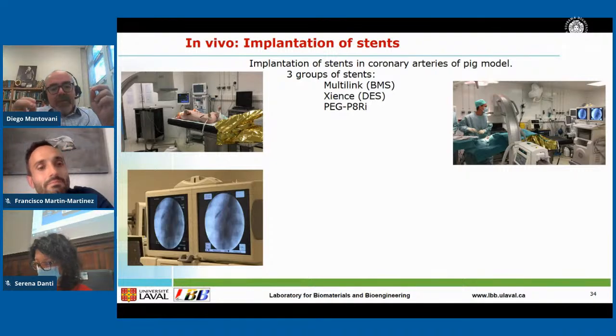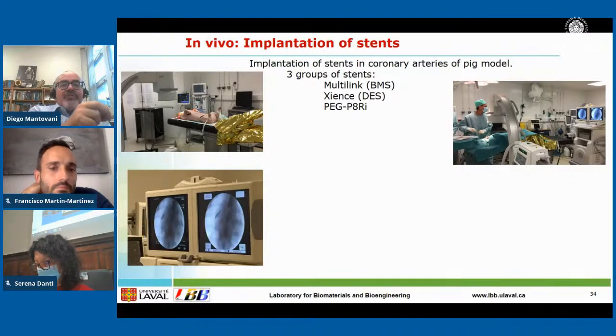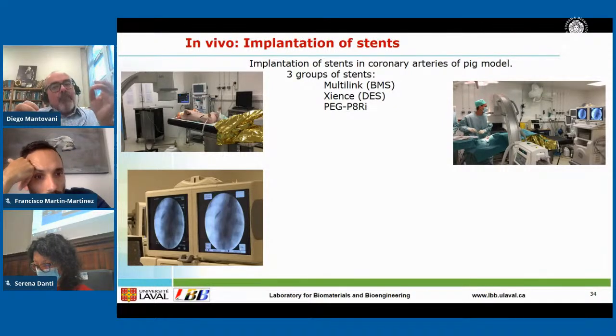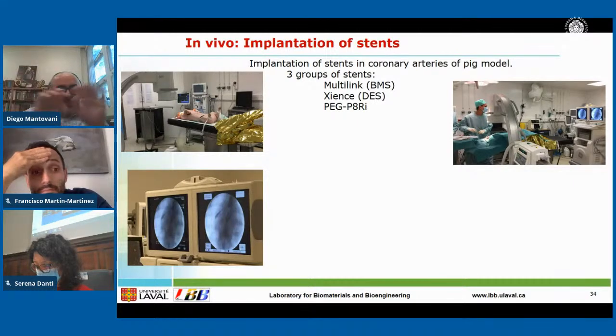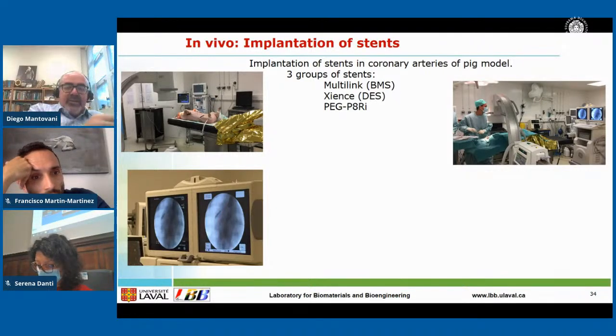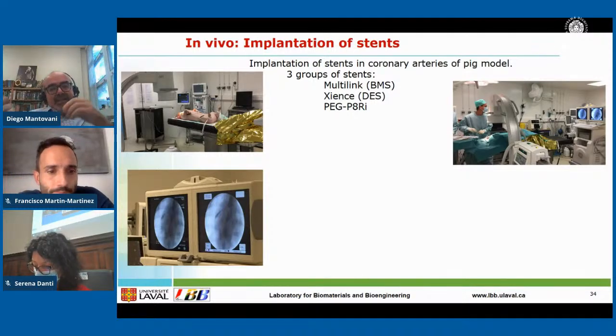So that's why a bare metal stent today, for a middle-aged patient, is considered the gold standard for rapid endothelialization. A drug-eluting stent, for the same patient, is considered a negative control. No stenosis within 6 months, but after 10 years, completely unbalanced hemostasis. So that's why, comparing with a bare metal stent that does not have any peptides, any molecules, any delivery, and a drug-eluting stent that, yes, has a drug releasing, but at the same time we know that at medium term, 5 to 10 years, complications will arise.